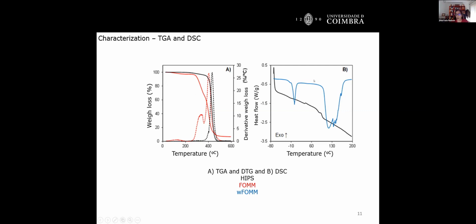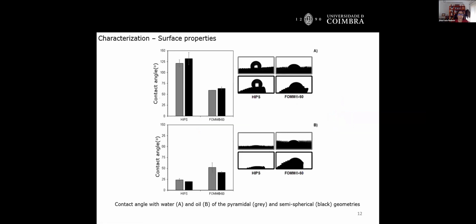For the DSC, what it shows you is that, as expected, HIPS is amorphous, and the washed foam is semi-crystalline because you have, well, a little bit complex melting temperature for the washed foam. Nevertheless, you are going to print the non-washed foam because you need some hardness of the filament to be printed, okay? And of course, then you need to characterize it. As you see here, you have HIPS and foam. You see really the roughness of the surface due to the low quality printing.